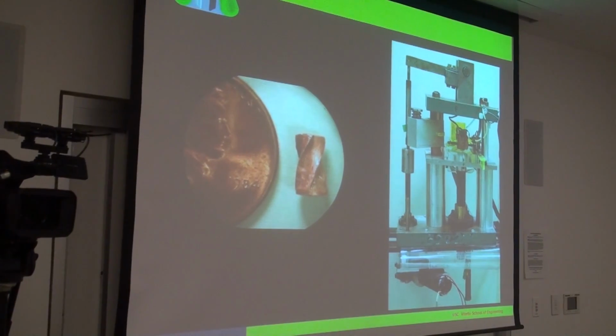Even today, if you were to build some small object like this, it's going to take an hour or two on these machines, simply because they use very thin layers successively, and every layer needs some kind of processing. You have to do material delivery and then some kind of processing in order to fabricate that layer and continue on. So I thought a lot, and I concluded that there's really no way other than increasing the layer thickness in order to increase the speed.